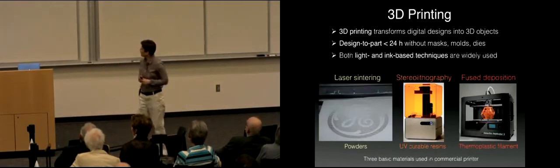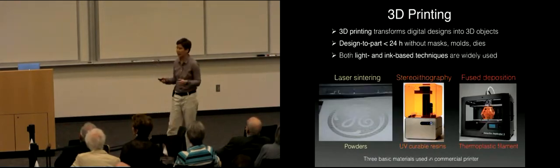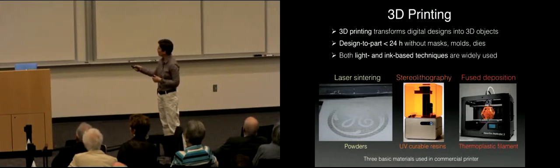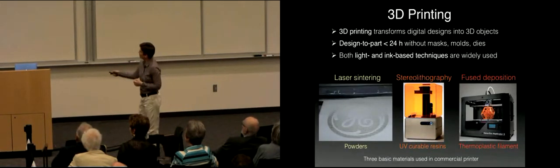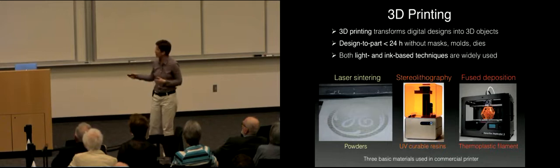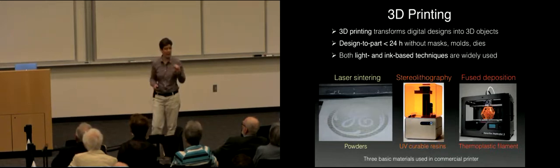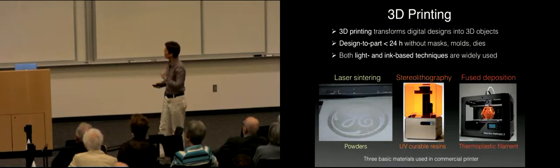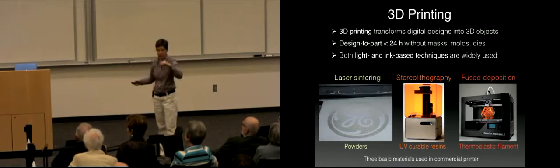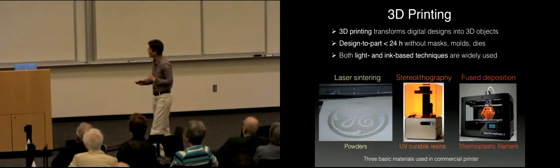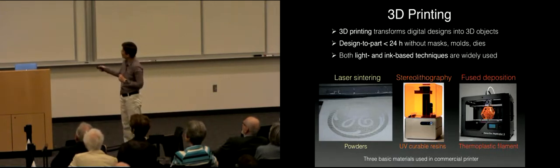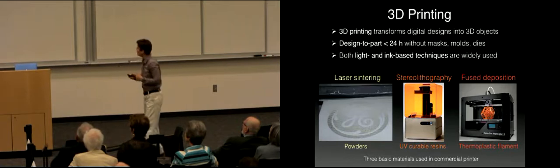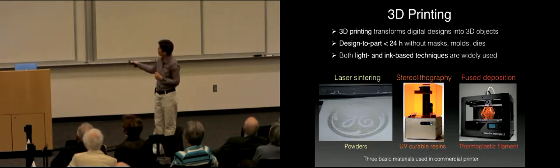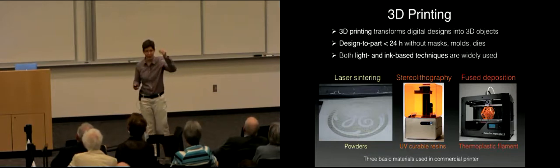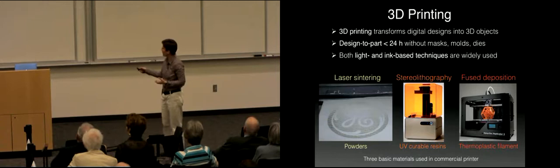So let's look at the types of printers that exist in the ecosystem. Some of you here have probably used desktop versions, MakerBots, Formlabs. This is a commercial large-scale printer. These two here are on the order of a few $1,000s a printer. This one is about $1.5 million for one printer. What's the difference? Well, here we're using a very high-powered laser to locally melt powder together, and I'll describe that in a little bit more detail on the next slide. Here we're using light to UV cure polymer resins. And here we're using a hot glue gun, essentially, to melt a plastic material, print it out onto something that cools very quickly and solidifies.